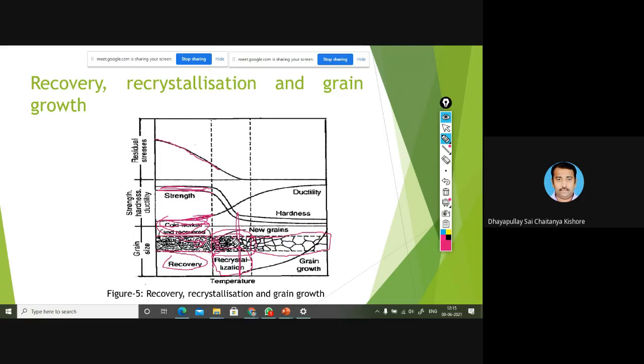You can observe clearly from this particular zone that the size of the grains is increasing slightly, and when it reaches the grain growth zone, you can observe clearly that the grain size is continuously increasing. Whenever the grain size is increasing, it will improve the ductility, and you can observe a coarse, rough textured surface, and also the strength and hardness properties are reduced.